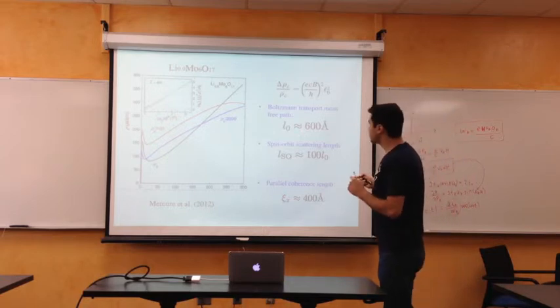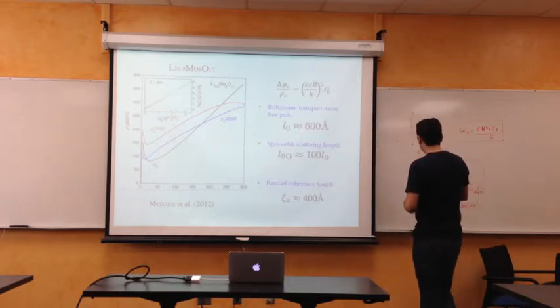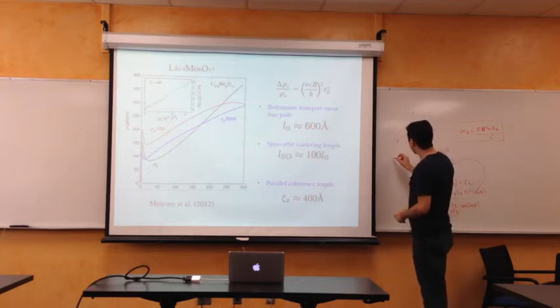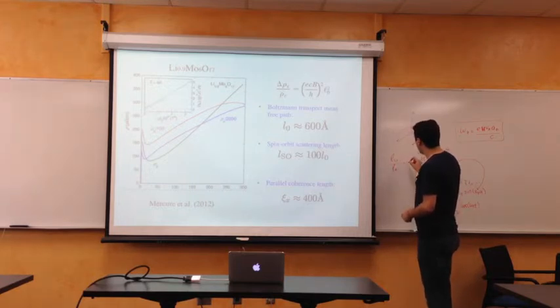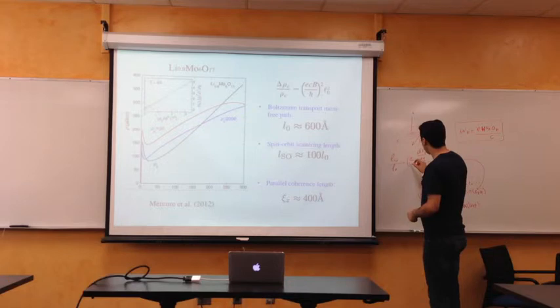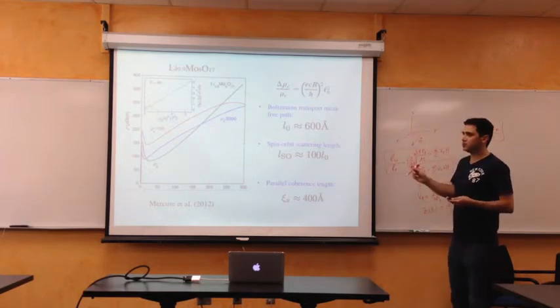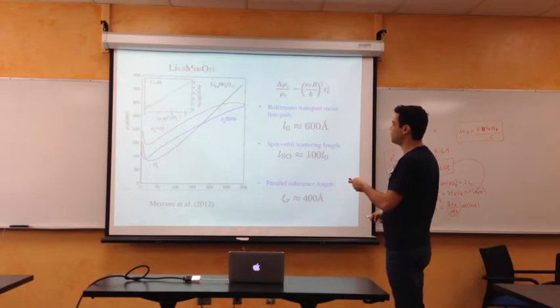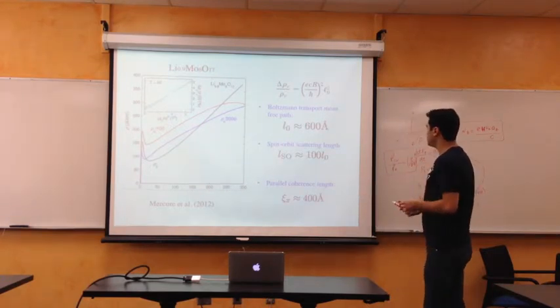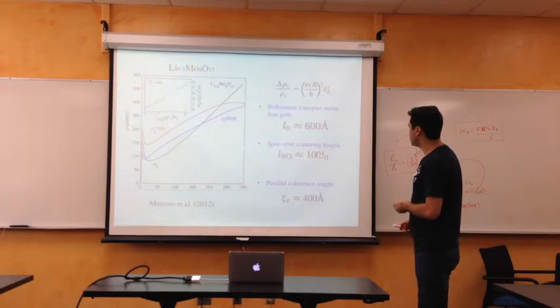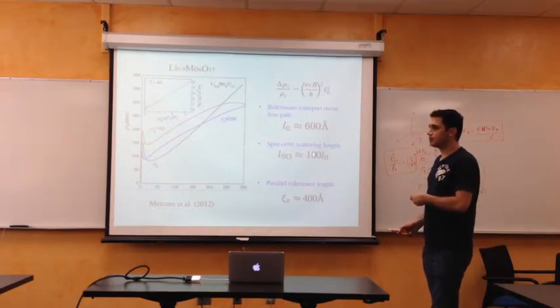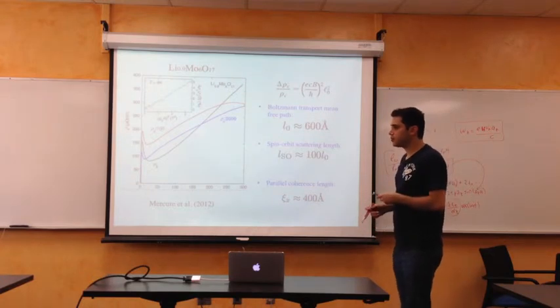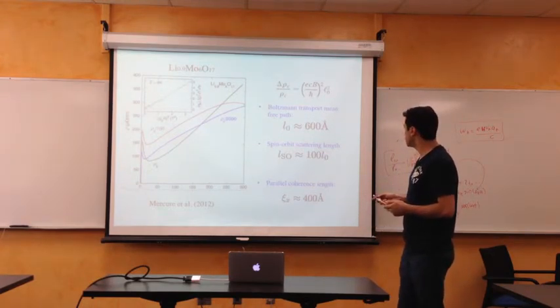And actually Abrikosov's formula relates the spin orbit mean free path to the Boltzmann mean free path as z over 137 - which is the fine structure constant - to the power 4. And z, for molybdenum, is about 42. So we get that the spin orbit mean free path is 2 orders of magnitude longer in this case - so it's essentially impure, no impurities in this.